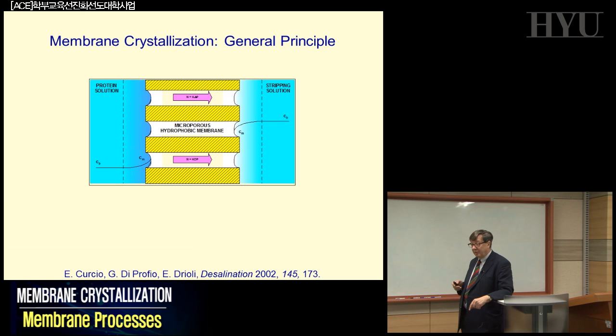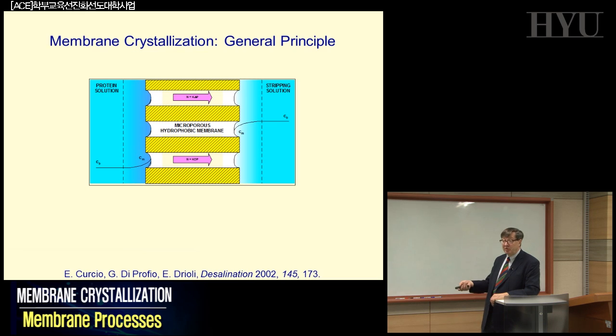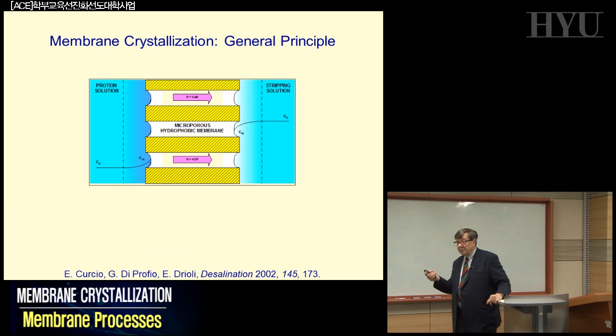If you do the same work with membrane distillation, we learn that basically increasing the concentration at the membrane solution interface does not significantly affect the driving force in the transmembrane flux, which is just because in evaporation it's a totally different mechanism, and you just have a small delta T that is moving the molecules in vapor phase across the porous membranes, so there is not the same effect. Eventually, you can have an effect in terms of viscosity, which increases if you increase the concentration very much, or you can reduce the activity, and that reduces the vapor pressure difference, but the effect is not the same as in reverse osmosis. So basically, we concluded in membrane distillation that the transmembrane flux is roughly constant with increasing feed concentration.